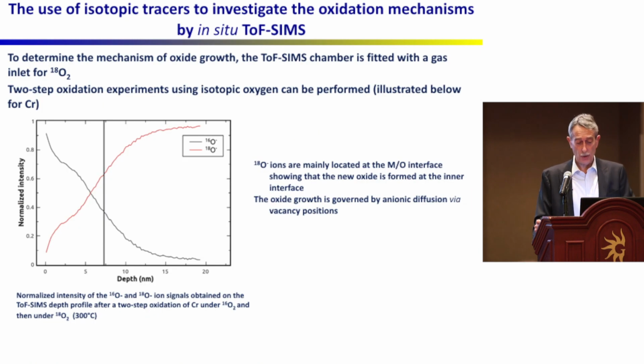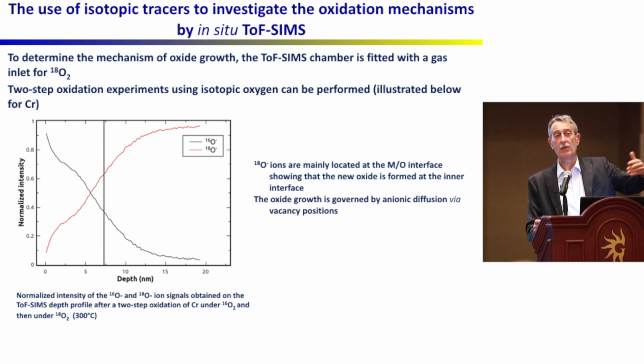As a sort of proof of concept, the first experiment we did in situ was to take a chromium sample, oxidize it in oxygen-16, stop the oxidation, very quickly change the oxygen-16 to oxygen-18, all that in situ, and then look at where the oxygen-18 is.